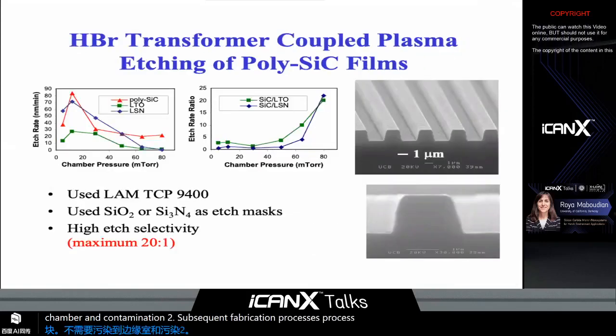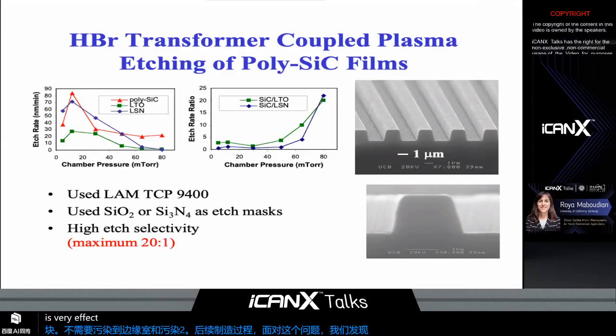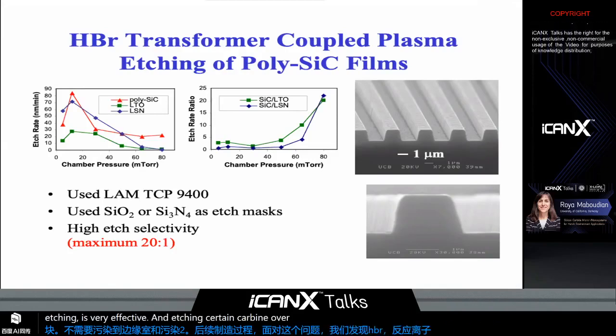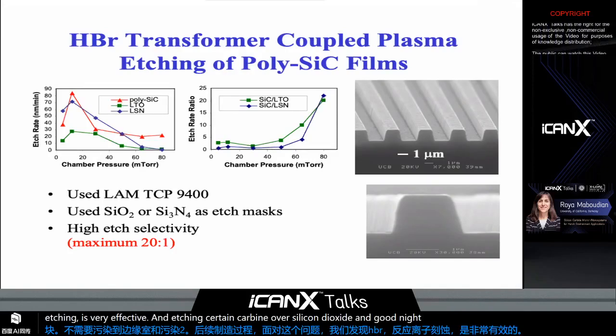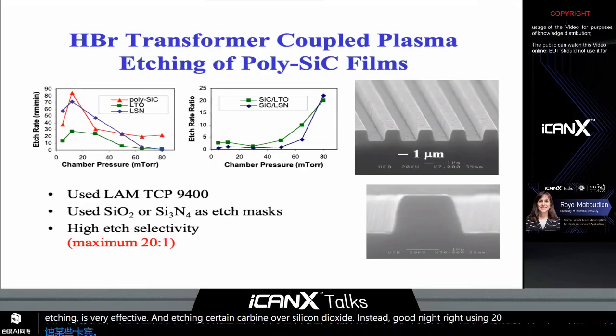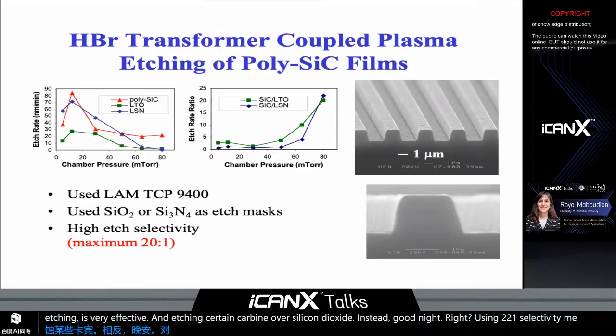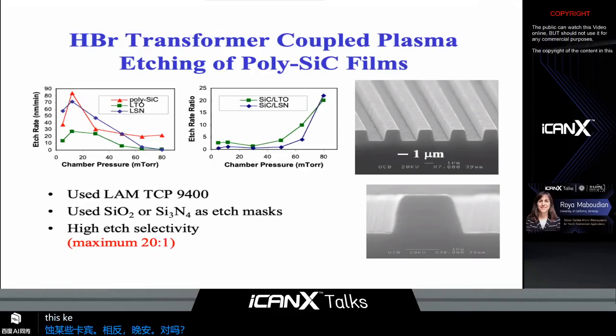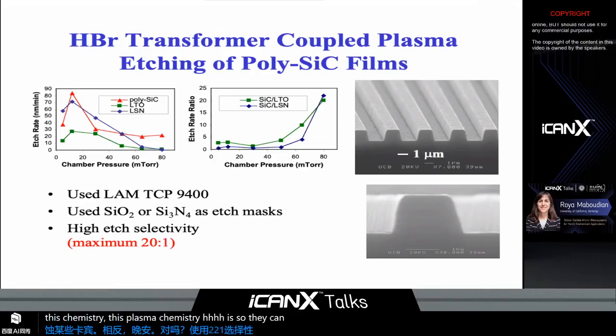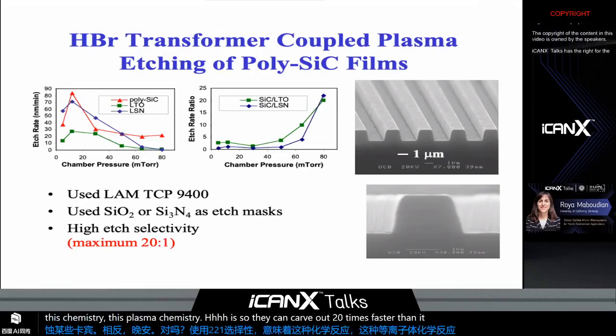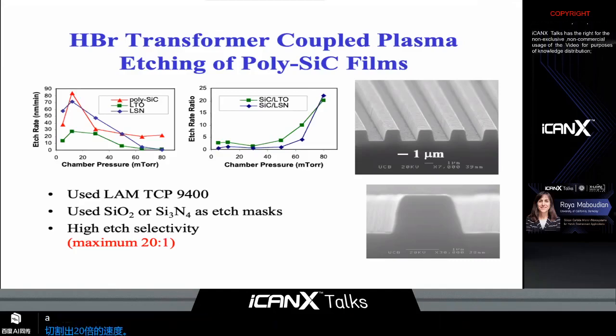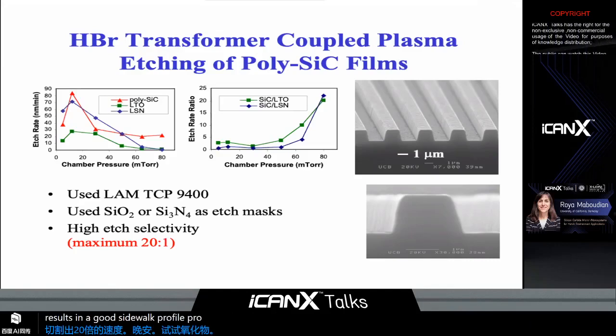Faced with this problem, we discovered that HBr reactive ion etching is very effective at etching silicon carbide over silicon dioxide and silicon nitride, yielding 20-to-1 selectivity, meaning this plasma chemistry etches silicon carbide 20 times faster than it etches silicon nitride and silicon dioxide. And it results in a good sidewall profile, as shown here.